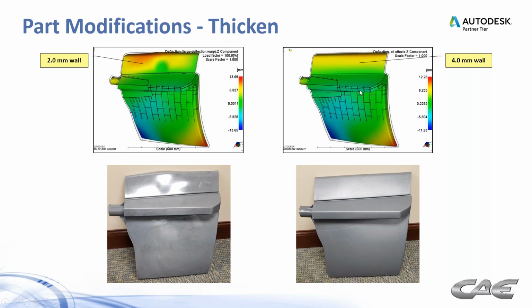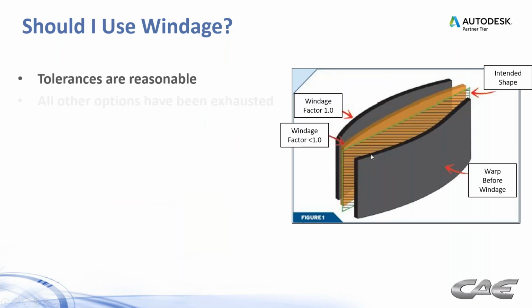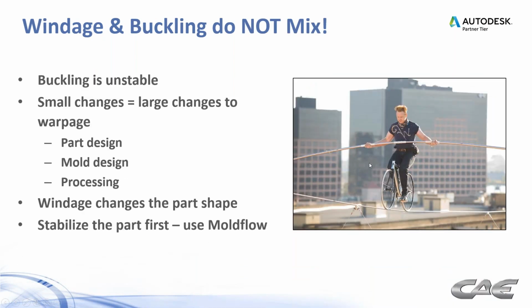But if we had gotten to this beforehand, there's still some warpage left on the bottom edge of this part here. Luckily, the assembly allowed for that to be okay, but if they needed to correct that, that might have been a windage solution. We stabilized the buckling, but now there's still some warpage left to take care of. So that's the main point with buckling parts: you've got to stabilize the part first before you get to the windage solution.